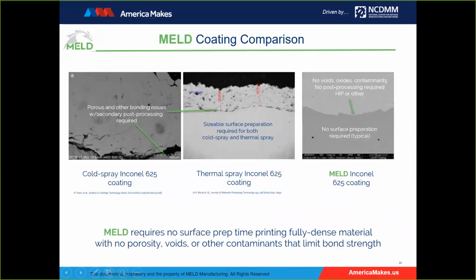I'm going to get into some coating. I just do a family of repairs, many more, but I'm time limited. So here's an example of coating. We start off with the traditional cold spray, thermal spray, and MELD, all using Inconel 625. I've got a series of about 5 slides coming up on a project that hits all the highlights of the MELD process benefits. So I look at cold spray and thermal spray, and you see the traditional challenges with the technology in terms of voids and porosity and so forth.